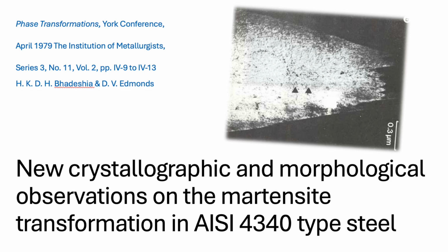Okay. So thinking about where this leads. Well, it raises a really interesting question for you to consider, doesn't it? We know elements like nickel are added specifically to lower that transformation start temperature, shifting the Ms to Mf range. So given that the lath packet seems to be the preferred low-energy structure, especially perhaps at lower transformation temperatures, and plates might be favored higher up, how could you perhaps tweak the alloy composition? Maybe slightly more nickel, or altering the molybdenum? To deliberately push the transformation towards favoring more lath packets, or perhaps even suppressing plates.